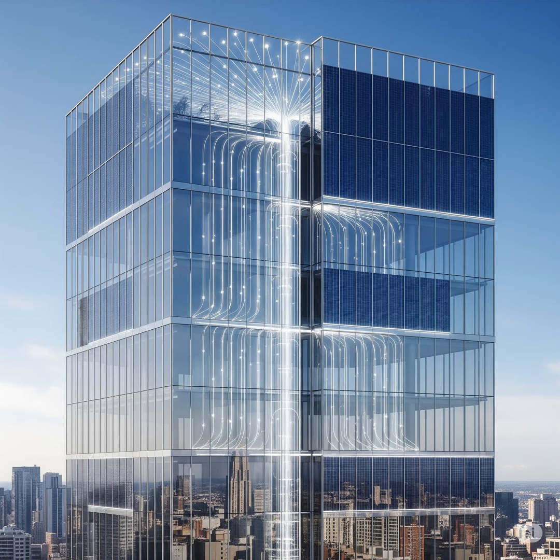Back and forth a few times, and it wasn't working nearly as well. Why was that happening? The likely culprit was that methylamine. It seems it wasn't fully returning the perovskite to its original perfect crystalline arrangement each time it cooled down, so you got degradation. I see. So that instability really killed the long-term potential of that specific design.